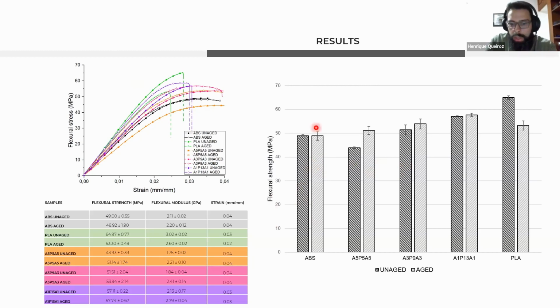And so when we look at the unaged flexural strength, other than this small dip here, we have a tendency of a quasi-linear increase from our pure ABS here to the pure PLA. And again, this is expected because as we have less ABS close to the outer layers, which are maximum tension and compression, we are going to increase the flexural strength. And also, the variation in the flexural modulus is also more significant for the same reason, right?